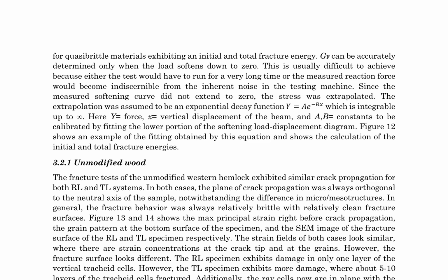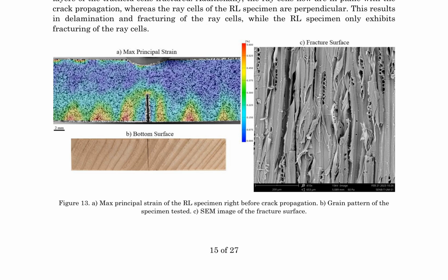Strain fields before crack propagation, grain patterns at the bottom surface of the specimens, and scanning electron microscope (SEM) images of the fracture surfaces were analyzed for both RL and TL specimens. The strain fields appear similar in both cases, showing strain concentrations at the crack tip and at the grains. However, the fracture surfaces differ significantly. In RL specimens, damage is confined to a single layer of vertical tracheid cells, whereas TL specimens exhibit damage across 5 to 10 layers of tracheid cells, leading to delamination and fracturing of ray cells.